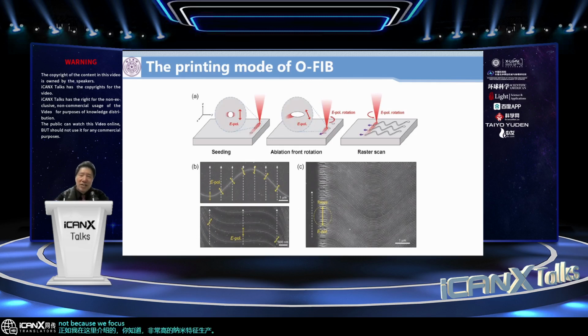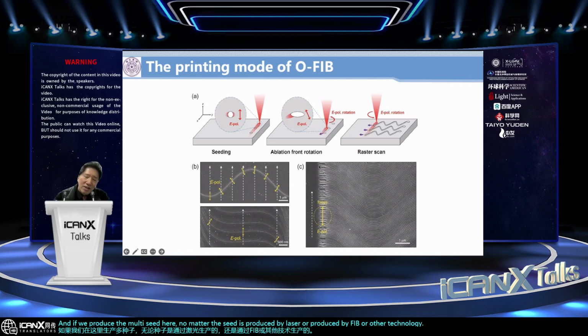As I introduced, the very high nano feature production is not because we focus the laser to a very small size, but it depends on the existence of the seed. It means for parallel fabrication, we don't need multi-head or multiple laser beams. If we produce multiple seeds, no matter whether the seeds are produced by laser, by FIB, or other technology, once we have such a seed array, we use wide field irradiation. We can rapidly produce many of these nano features.